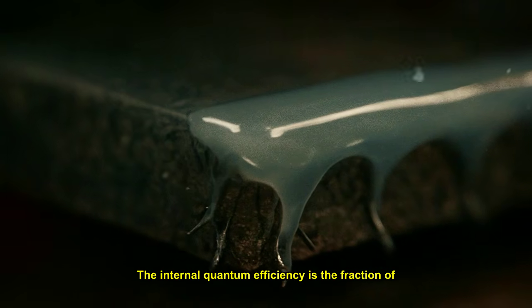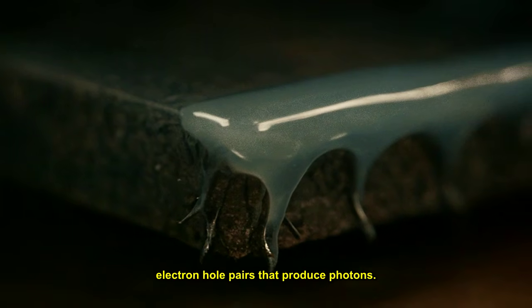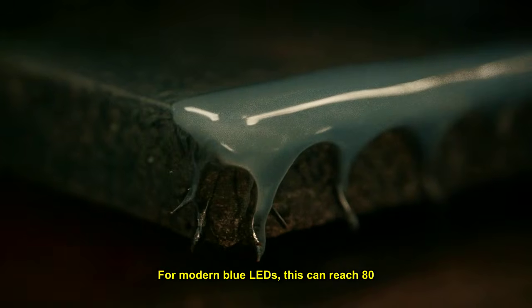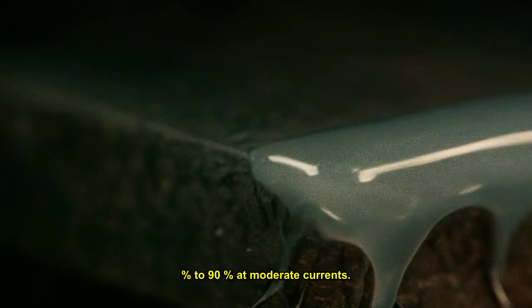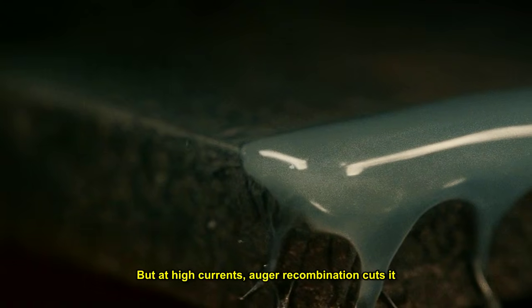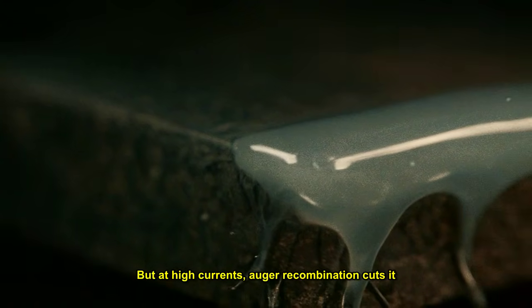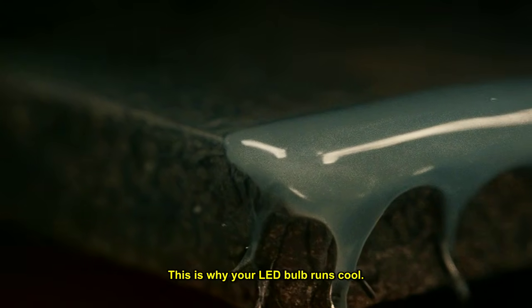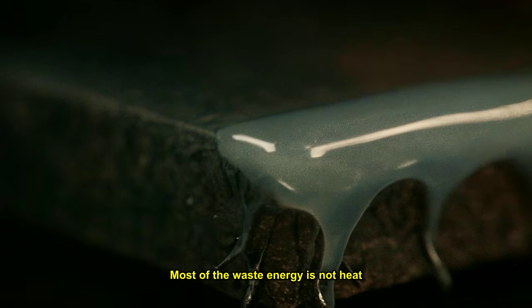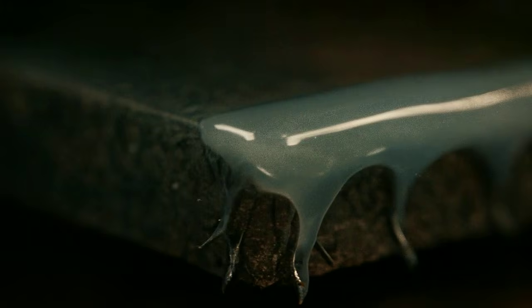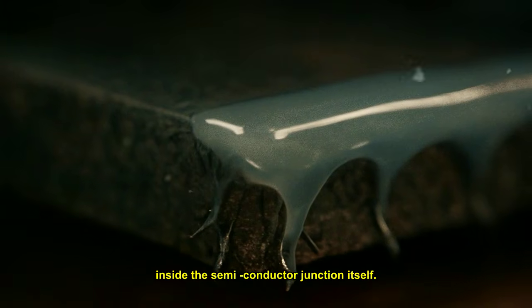The internal quantum efficiency is the fraction of electron-hole pairs that produce photons. For modern blue LEDs, this can reach 80 to 90% at moderate currents. But at high currents, Auger recombination cuts it down. This is why your LED bulb runs cool. Most of the waste energy is not heat from resistance. It is energy lost in non-radiative recombination inside the semiconductor junction itself.